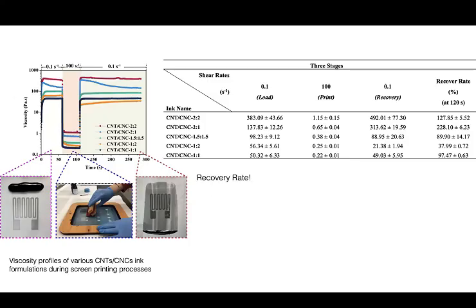This is a very good representation of the printing process. How it works: you pour your ink, which in this case is the whitish region of the structure, over there. The ink sits there and doesn't spread quite easily. You don't want that. So you have a fine, silk-like mesh structure. Using a tool, this is a very simple representation. The semi-automatic printers do this automatically, but you also need to pour the ink in there. Then you squeeze the ink, which is the second phase.